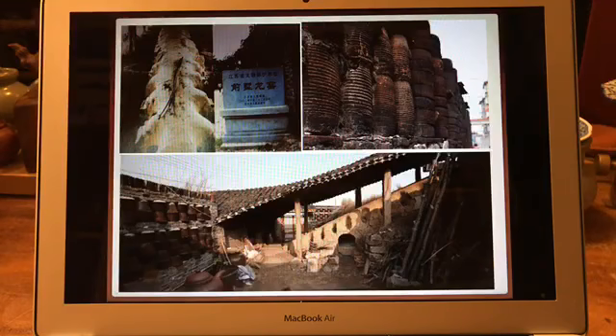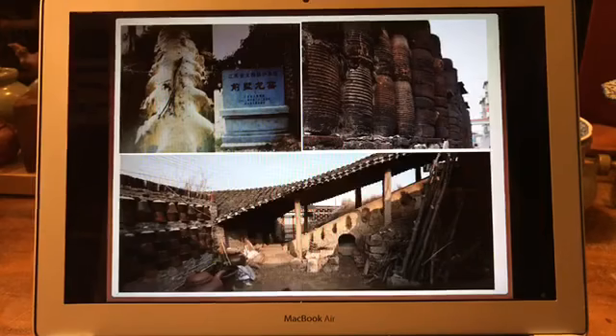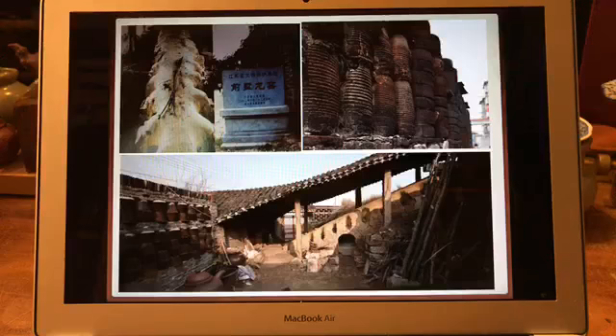At the same time, most of the Yixing teapots from history were fired in what we call containers, or a kind of cistern, so that the ash and the dirt from the wood firing in the dragon kiln will not contaminate or spoil the surface of the teapots. So if you see a lot of very high end or very nice Yixing pots from the early Qing dynasty, you find that the surfaces are almost typically flawless. Yeah, that's because they fired in the cistern.